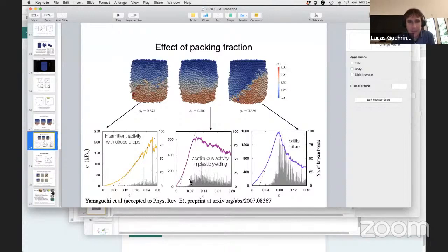There are spikes here versus a more continuous behavior. So we would describe this as more intermittent in the mathematical sense, but we don't have a formal proof for that because the sample statistics size is just too small. We couldn't upscale the numerics to cope with the hundreds of thousands of particles we would need to make that more rigorous. There is some work by Ferenc Kun's group on similar materials. I don't think he looks at the density, but at least in the brittle case, he looks at the statistics before and after brittle failure and shows that they are different. We would love to have done that, but sample sizes were just too small to make it statistically significant. We suspect it's there, but yeah.